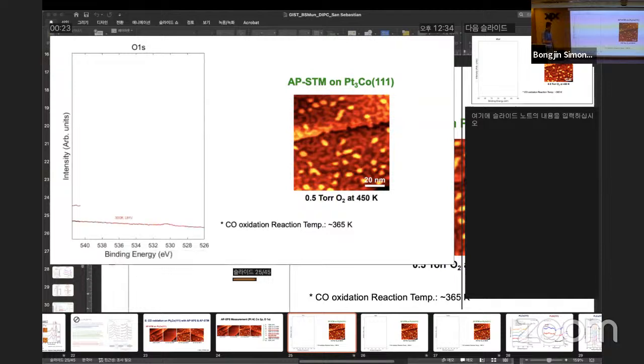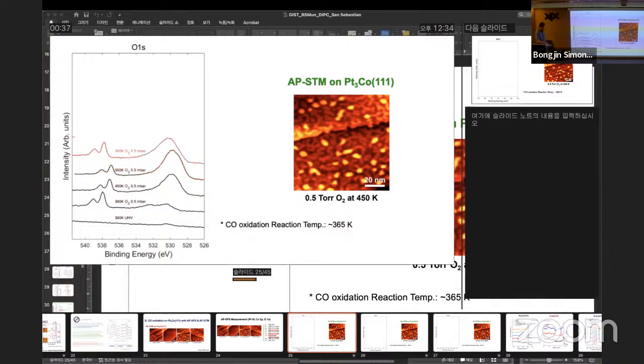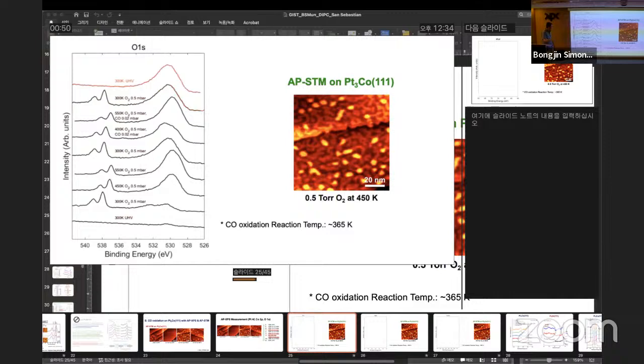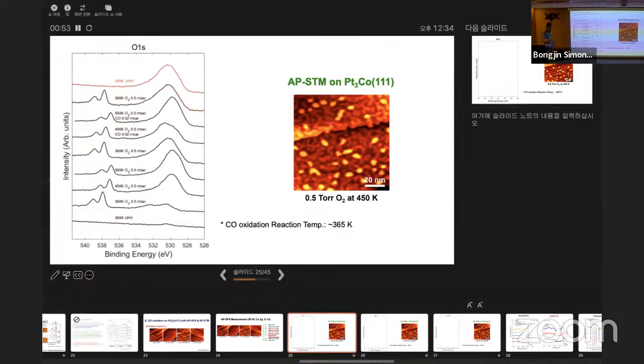We cleaned the crystal. I'm showing you the oxygen 1s, and when we introduce the oxygen, you start to see the gas phase of oxygen with the small oxide. And when you introduce the oxygen up to about 500 millitorr while increasing the temperature, you can clearly see the formation of oxide. Then you reduce the oxygen, and I introduced a small amount of CO. As soon as you introduce the CO, you start to see the oxide change completely. When you increase the temperature further, it changes a little more. But when you bring the temperature down, it goes back, and this oxide remains on the surface.